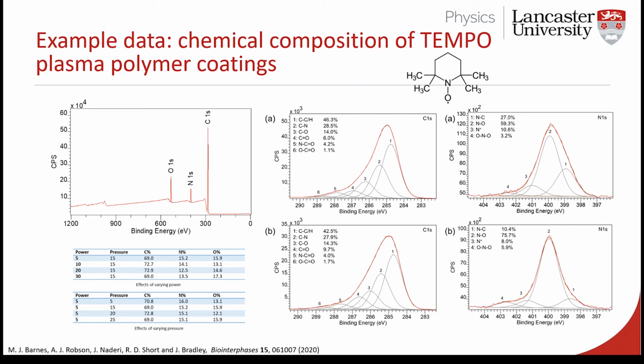One of my favorite examples actually of the use of XPS was when I was working in Brisbane a few years ago. And one of the local breweries came to us, and they couldn't understand why the beer, it was the Castlemaine brewery, they couldn't understand why the beer was going flat in their new plastic bottles. And through the chemical analysis, through the XPS analysis of the bottles, we found out that there was an excess of oxygen in the polymer of the bottle, and the oxygen was replacing the carbon dioxide in the beer, and so the beer was going flat. So they had to go off and change their plastics, their bottles. So again, real world examples of how this can be used.